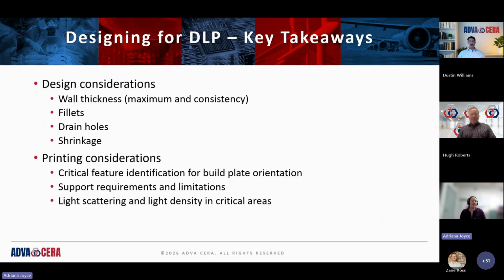Overall, the things I'd like you to remember as you're designing and working with parts for ceramic additive manufacturing is that the wall thickness is a material limitation. We have a maximum wall thickness based on the raw slurry. So adding lightweighting features, making sure that wall thickness is consistent all the way across the part will help us get a successful part out. Use fillets as large and as often as possible, and add drain holes anywhere that you can so that features are better cleaned and the internal features are more true to the design.